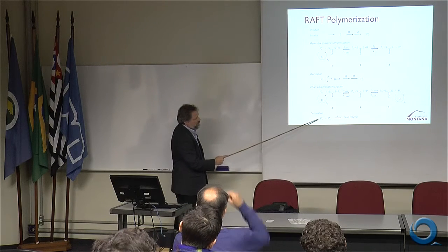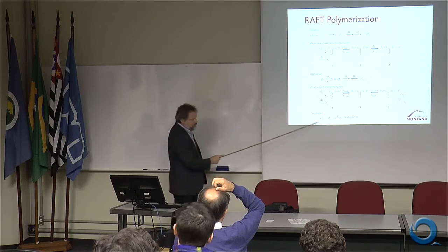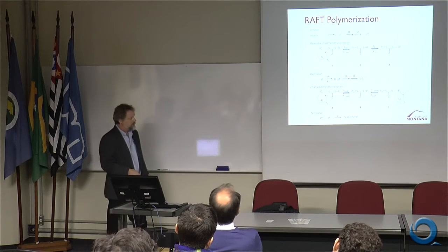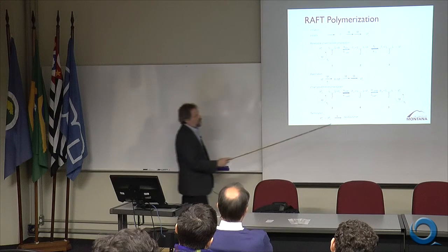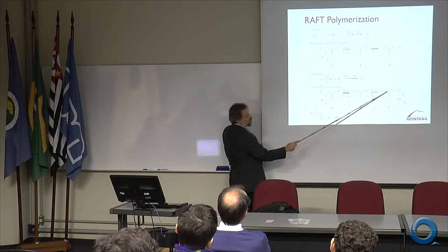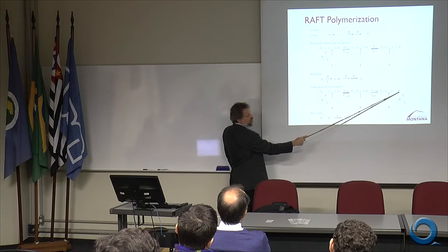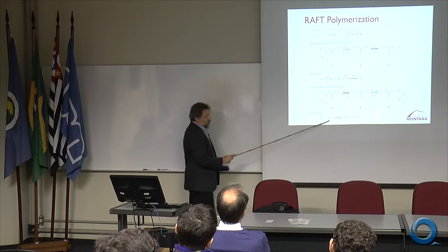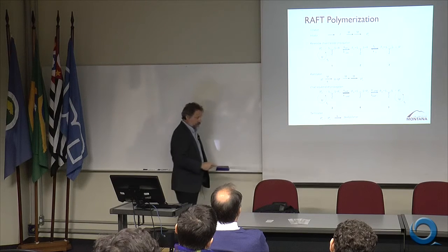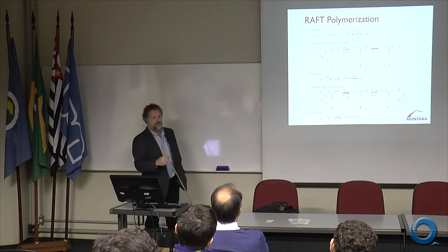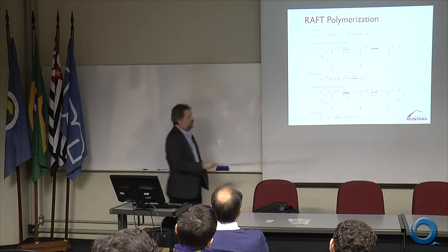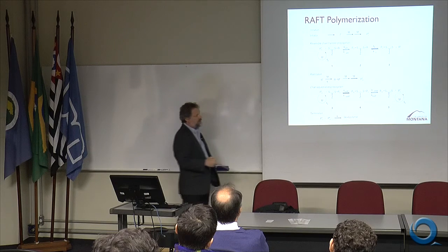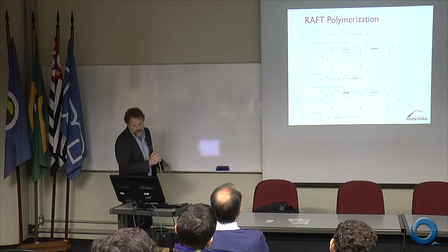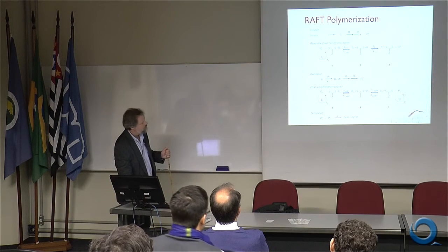Lastly, the concentration of these free radical polymers in solution is actually very low. Remember, most of the polymer growing chains are in this form, and only a small concentration is in this form. So the chances of those two polymers finding each other and terminating to form a dead polymer are actually quite low. So this process happens, but it's not a major part of the polymerization process.